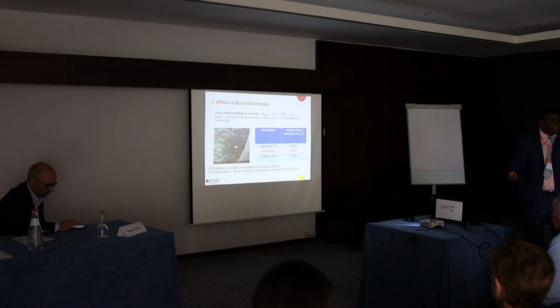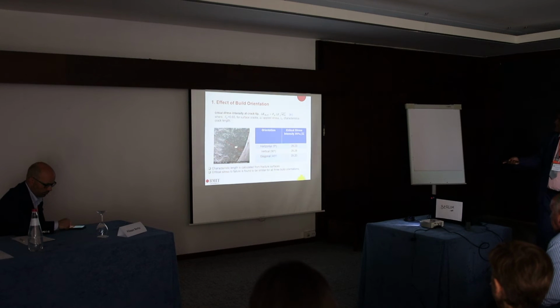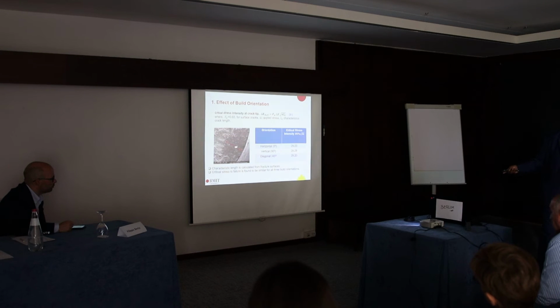That is our belief. These are the data which show you the build orientation has relatively little effect on the fatigue. But to confirm that, we always go to the fundamental fracture mechanics, and we did a critical stress intensity factor calculation using this formula. We calculated the critical length by measurement from the SEM micrograph. When we use this critical length and F, the factor 0.65 for surface crack, we found the critical stress intensity is the same for horizontal, vertical, and 45 degree build. So that explains fundamentally why we do not see the effect of build orientation.